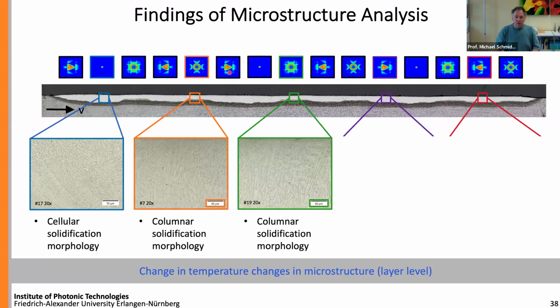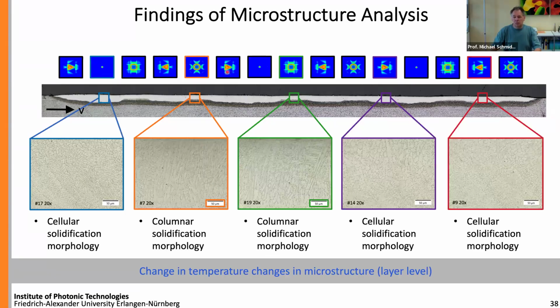But as well, as mentioned, we have different weld pool depths that we create, especially for the larger ones, this one and the quadratic shape. They create shallower molten pools, whereas the other ones create deeper weld pools. And as you probably might expect, this results in different microstructures.